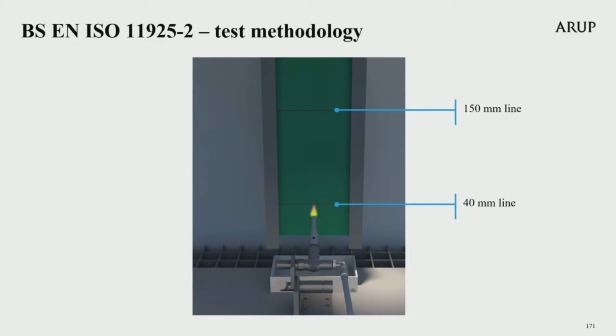The flame is then applied to the material for either 15 or 30 seconds, depending on the classification the sponsor wishes to obtain. The higher European Class B down to the European Class D are based on a 30-second exposure. Once the flame is applied, the extent of vertical flame spread is observed and recorded. The image here is from a test video that we'll watch in a few moments.